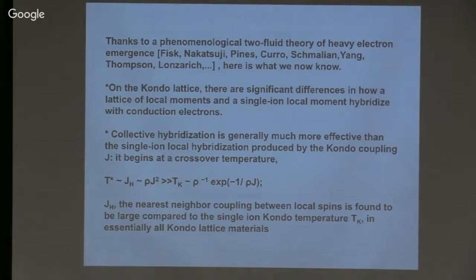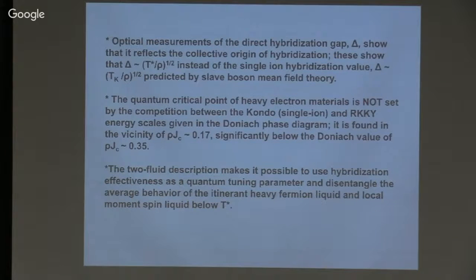In other words, instead of a single local moment hybridizing against this background, at least a pair of them must go at the same time. They're typically of opposite spin. So they hybridize together as a result of their interaction. It's a very different kind of instability than the Kondo instability. And this is the reason why it's been extremely hard to develop a microscopic theory of heavy electron materials.